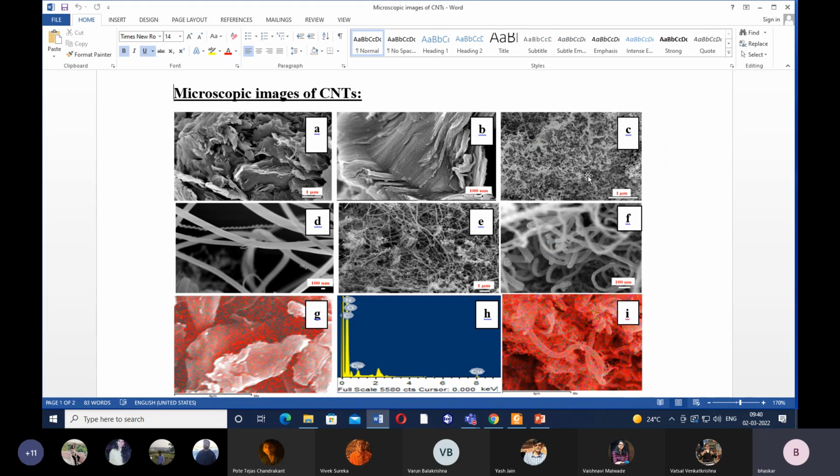Why not more? From the SEM images, I showed them that if I carry out the reaction at high temperature, then there would be melting of the copper particles. From the SEM image you can easily detect this. So I can show people that melting of copper nanoparticles took place at a temperature beyond 350 degrees Celsius.